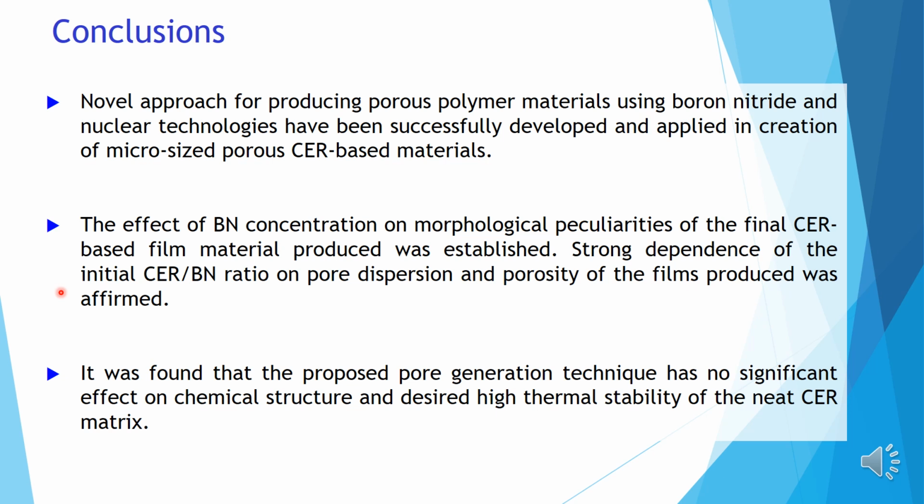Strong dependence of pore dispersion and porosity of the films produced on the initial CER-BN ratio was affirmed. It was found that the proposed pore generation technique has no significant effect on chemical structure and desired high thermal stability of the neat CER matrix.